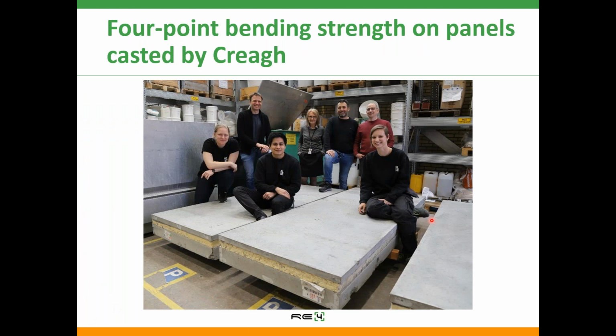Ruben has already shown pictures from the upscaling work, and the first step in the upscaling was that they used the mixes that we developed, and they made some adjustments. But the interesting thing was that even though they used another type of cement, another type of primary aggregate, other fillers, and other admixtures, the only thing they needed to adjust was the amount and type of superplasticizer a bit. They used the same CDW because CDE delivered CDW from the same batch to us and to Creagh. So this was really interesting. These are the 3 large elements from the first upscaling for test elements, and this is part of the crew at RISE who has helped me, or to be honest, they have done the work. I just sit there.